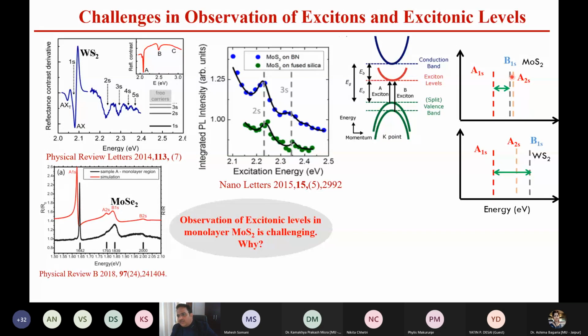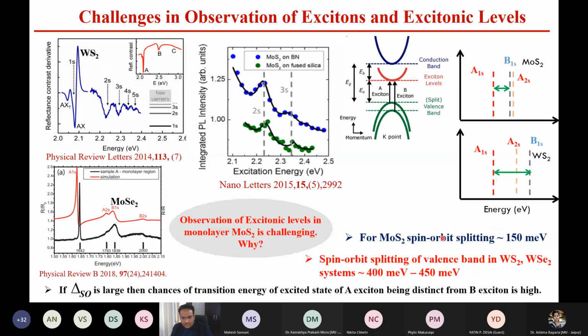Okay, so these peaks, the excited states of the A exciton, are difficult to observe using normal photoluminescence spectroscopy or something. Yeah. So it is very difficult actually. Okay, but what we try to understand is that it is not only the... so the spin orbit gap is large in WS2, so we are able to see the excited state of the A exciton in WS2, but it is difficult to see in MoS2.